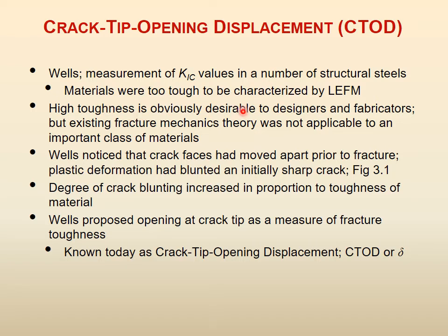So high toughness is definitely desirable, but existing fracture mechanics, LEFM, was not applicable to an important class of materials, right? Structural steels are pretty ductile steels. They have a good value of toughness. This toughness is a highly desired thing, but the LEFM theory available at that time was not good for these materials. Wells noticed that the crack faces had moved apart prior to fracture. There is a crack and it is opening, right? The faces of the crack are moving away from each other before fracture.